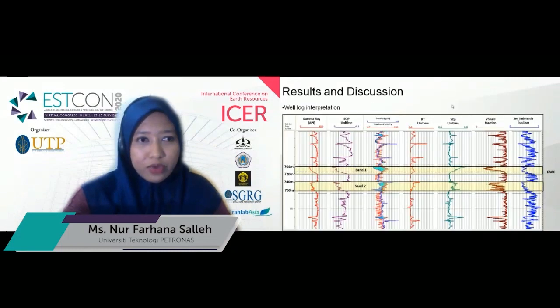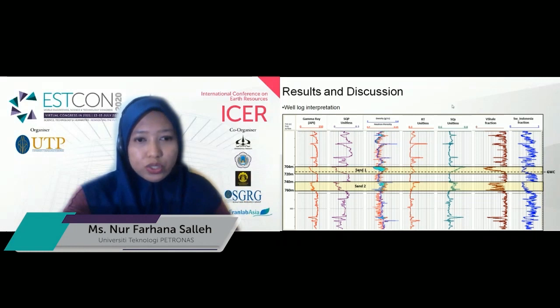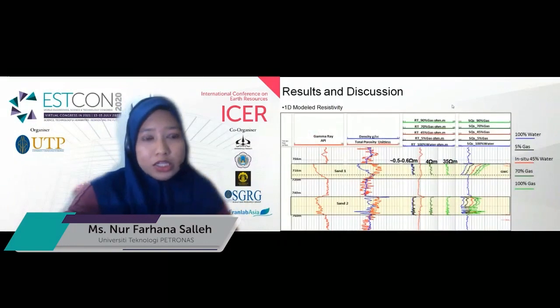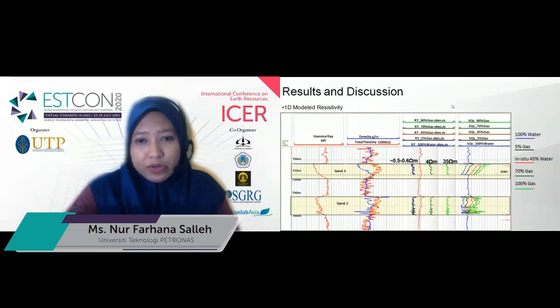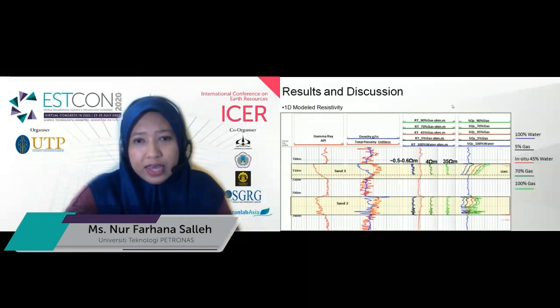So this is the result of our well log interpretation. There are two sand layers identified, sand 1 and sand 2, with a total thickness around 32 meters. And this is the result of our 1D model resistivity. We can see there is only a slight difference in the model resistivity between 100% water and 5% gas. The resistivity is noticeable at 70% gas and strongly increased at 90% gas, up to 35 ohm-meters.